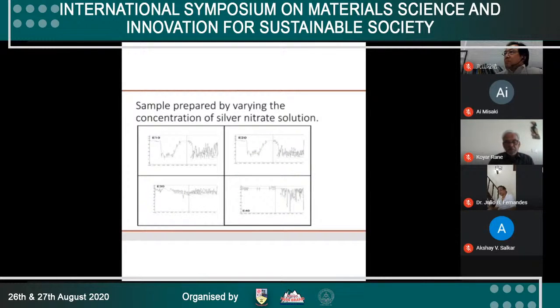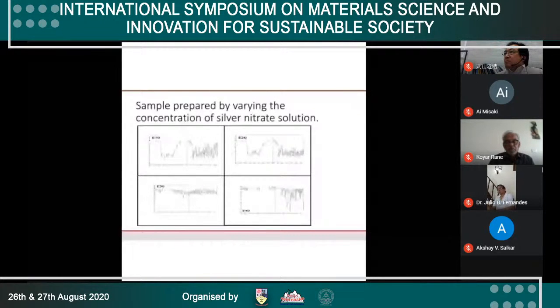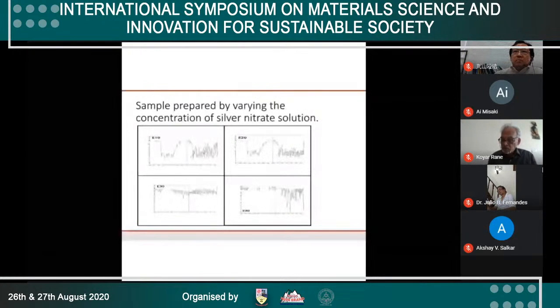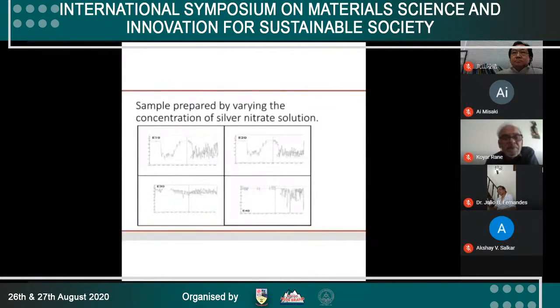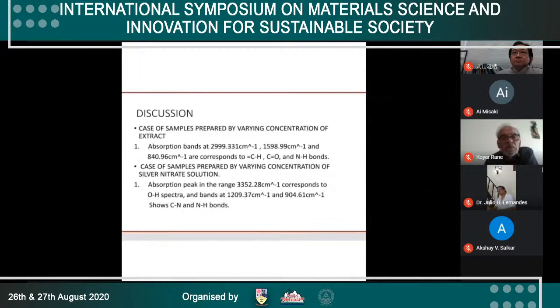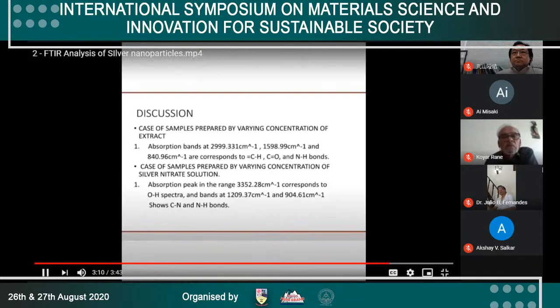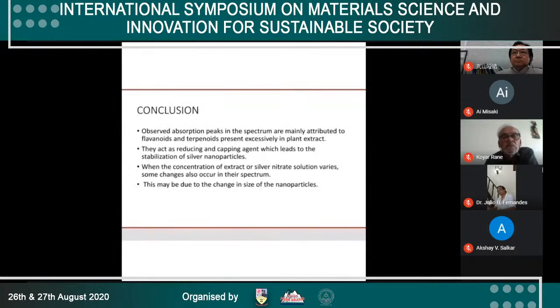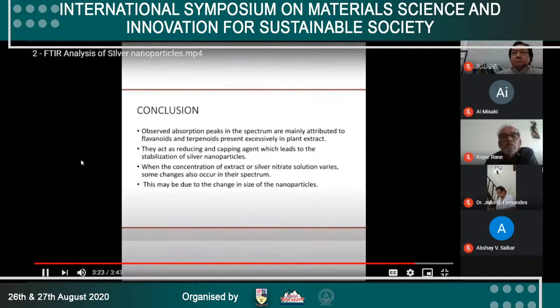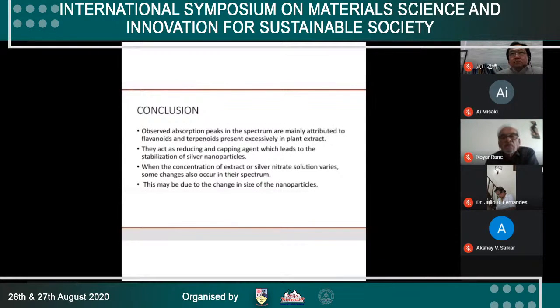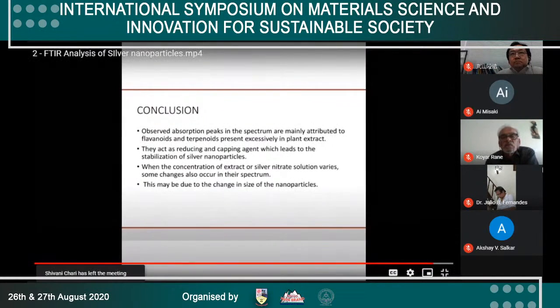Sample E40, which is prepared using 40 ml extract, shows an absorption peak at 3666.68 cm inverse, which represents alcohol or phenol, which is also moved towards a higher wavelength region. That is, when the concentration of extract or silver nitrate solution varies, the spectrum also changes. Other observed absorption peaks in the spectrum are mainly attributed to flavonoids and terpenoids present in excess in the plant extract. They act as reducing and capping agents, which leads to the stabilization of nanosilver. When the concentration of extract varies, some changes also occur in the spectrum. It may be due to the change in size of the particle.